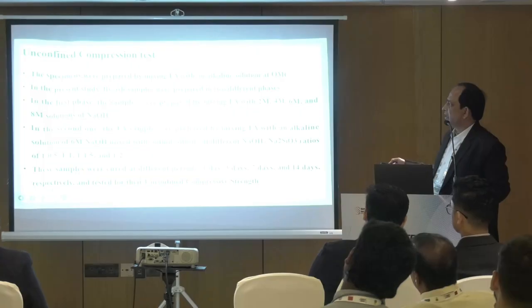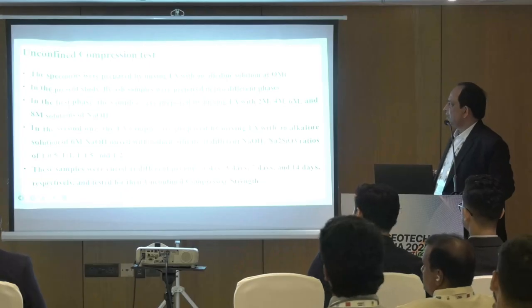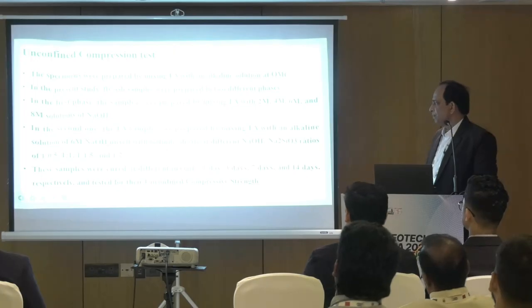Of course, there is some literature to correlate the propensity of erosion with the UCS. We have gone for different molarities of sodium hydroxide: 2, 4, 6 to 8. This is based on literature we tried. And in the second phase, we have taken not only sodium hydroxide but also sodium silicate, with different proportions of 1:0.5, 1:1, 1:1.5 and 2. And we have gone for different curing periods, 1, 3, 7 and 14 days, just to know the effect of curing on UCS.